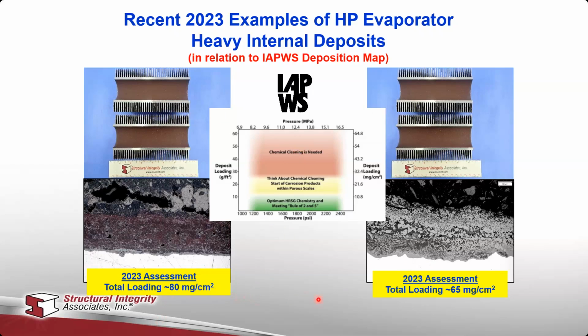So you can see in both cases here the deposit on the internal surface right here for this tube, and here's the deposit on this tube right here, and you can see that these levels are very high, 65 milligrams per centimeter squared and 80. And if you look at the deposit map, you'll see that these are right at the top of the red band. So this is a very dangerous situation for those particular plants, and they know that if you have some contaminant ingress, it will almost certainly result in hydrogen damage, in a failure.